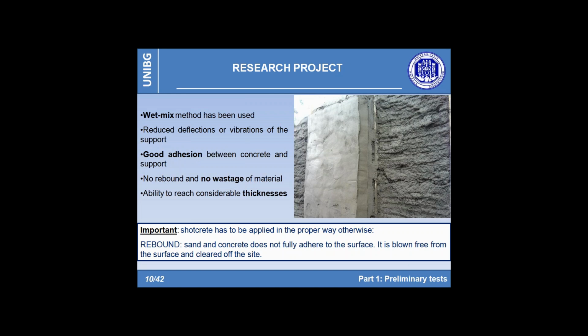In this case, neither any delamination between support and shotcrete nor sliding between two consecutive layers of shotcrete have occurred. This is due firstly to the mechanical characteristic of the developed cementitious compound that is homogeneous and sufficiently compact and with a very good strength capacity.